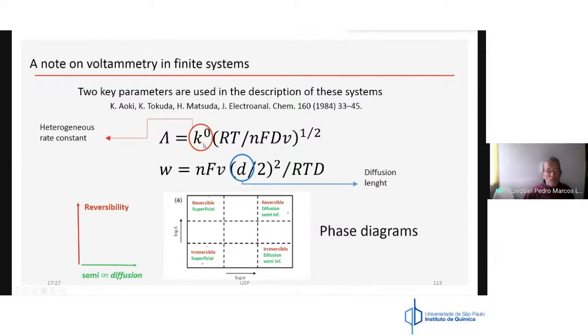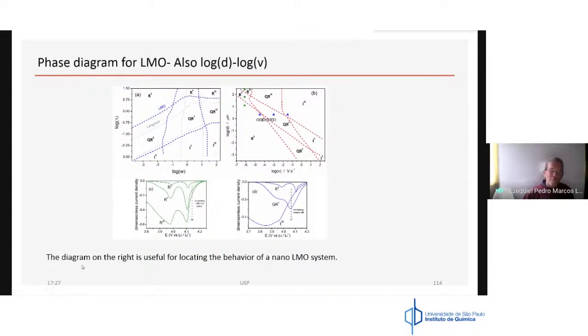So what people usually do is to make a phase diagram of reversibility, where depending on the relationship between the rate constant and the sweep rate, you get reversible or irreversible behavior of the system. And concerning the size of the system, you get a behavior which is called semi-infinite diffusion or superficial. So we made this phase diagram for this system, and this diagram is useful. For instance, here on the right, you can rate the behavior of this system as reversible or irreversible depending on the sweep rate, and you can rate the system as finite or semi-infinite depending on the size of the system.